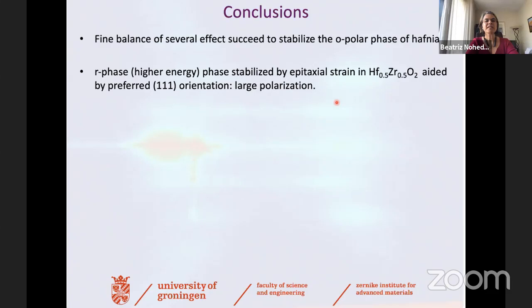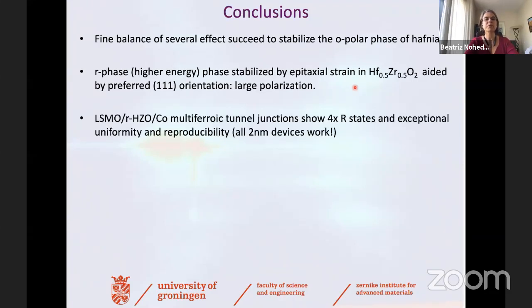So I would like to conclude by saying that one has to find a very fine balance of many different effects to succeed in stabilizing the orthorhombic phase, the polar phase in hafnia. And this has happened by chance, luckily, and we now can benefit from that. There is this rhombohedral polar phase, which is a higher energy phase that can be stabilized by epitaxial strain and has a very good interface with the substrate, and therefore is very convenient and advantageous for device applications, also because it has a very large polarization.